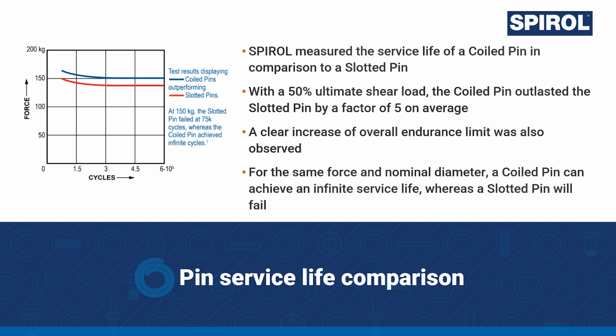So how do pins compare in numbers? We've performed in-house experiments supervised by renowned academic researchers on a machine which simulates a reciprocating shear force acting on the pin with adjustable load. In a scenario where the dynamic load was 50% of the pin's overall strength, the coiled spring pin lasted approximately 5 times as long as the slotted spring pin on average. Not only that, a clear increase of the overall endurance limit was also observed, which means that for the same force and nominal diameter, a coiled pin can achieve an infinite service life, whereas a slotted pin will fail prematurely.